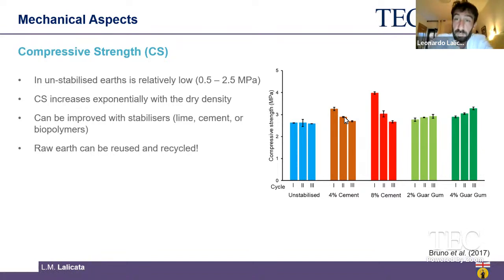reduction in the compressive strength, and this is because you are basically breaking the bonding that the cement gives to the materials. On the other side, the biopolymers show a slight increase in the compressive strength, but this is because the curing process of the biopolymers is much slower. So there is something that is still curing over time during these cycles. But the important general result is that you can use and recycle raw earth in both stabilized and unstabilized conditions.